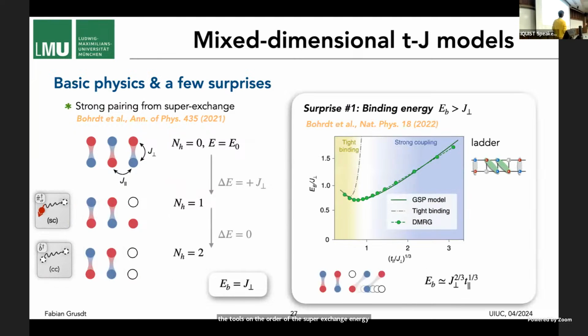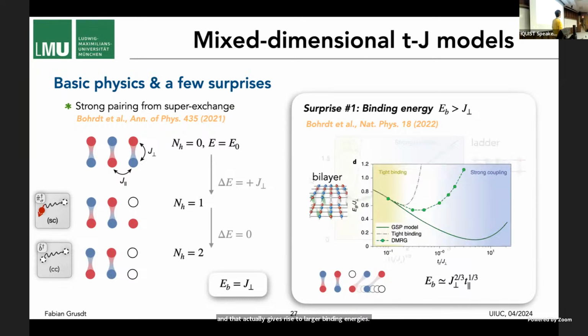Okay, now you can ask, does this picture still hold if you go and switch on the tunneling in the planes? And that's actually a large energy scale. It can be larger than the super exchange. And here's the surprise. It turns out the binding energy, first it goes down below the super exchange. And I'll just use my mouse since the pointer ran out of battery. But here you can see you get binding energies at large tunneling that are even higher than just the energy it takes to break up the singlet. And it turns out this has to do again with the string pattern that forms when the holes move around, because they tilt these singlets, form a string of tilted singlets, and that actually gives rise to larger binding energies. This is a DMRG simulation on a ladder. It also works in a bilayer, at least in a small one that we can access numerically. And that's great news, right? That you can get binding energies that even exceed the super exchange interaction between the spins.